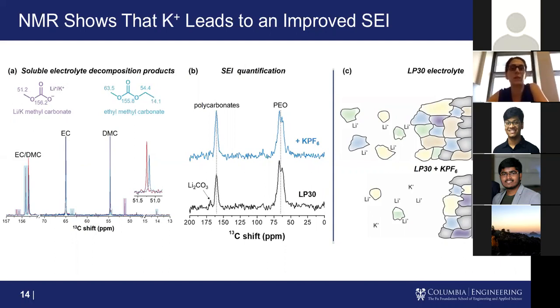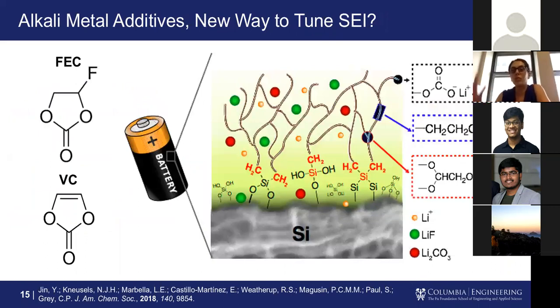So we were really excited by this result, mostly because it's a completely new way to tune the SEI. What battery manufacturers do in industry is they add these special carbonate molecules to the electrolyte. This is fluoroethylene carbonate and vinylene carbonate. What these do is they preferentially decompose over the other carbonates in solution, and they form these branch chain polymers in the SEI.